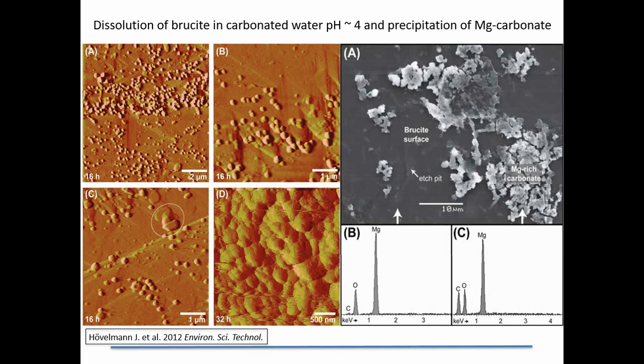there are etch pits there that you can see, and if we zoom into that in number C, the circle there, we can still see that the nanoparticles are clumping or merging together to form a new phase, which we've analyzed in SEM, EDX, and the base there is the brucite, magnesium with only the carbon of the coating, magnesium hydroxide, whereas the nanoparticle phase, the merging nanoparticle phase, is magnesium carbonate, because you can see the higher carbon peak there. So this is an example of what happens during CO2 sequestration. We have to have available ions, cations, at the surface to form a new carbonate phase. Okay.